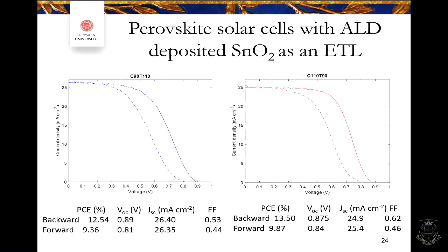So this is a solar cell deposited by slot die coating with the atomic layer deposited tin oxide. So now we have this large upscaled technique, or semi-upscaled slot die coating, with the electron transport layer. What you see here is the efficiency is not so good. We have a good current, I would say, but the voltage is rather low, though not super low. And you also see that the curve is not perfect here.